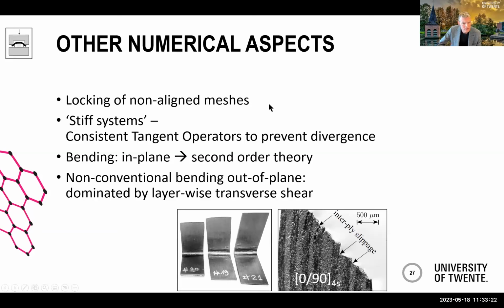Bending is another thing. If you've got bending in plane, you can imagine that the fibers are still resistant to in-plane bending as well. To describe that, you would need second order theory, where a previous lecture has gone into far more detail. And the out of plane bending is, I would say, rather unconventional. It's dominated by layer-wise transverse shear. If you look at these L shapes and inspect the edges here, you can see considerable transverse shear and also slippage between the plies. So this is quite different from what an ordinary Kirchhoff or also a Mindlin element would do. So that also requires a bit of attention, to say the least.